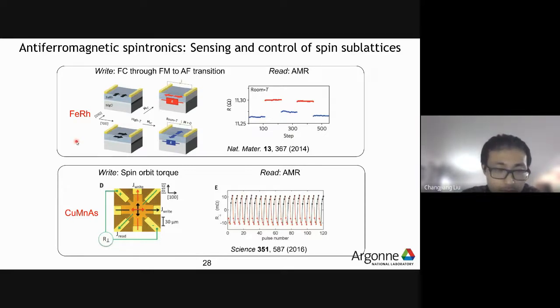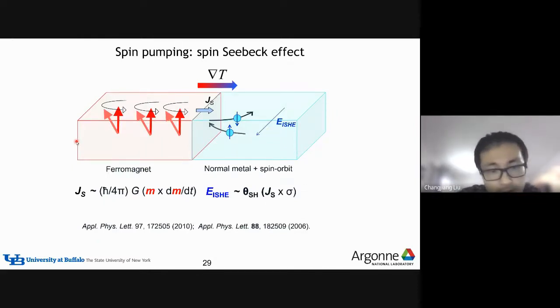So the experiment I will be talking about is based on spin-Seebeck effect, and microscopically, this spin-Seebeck effect is related to spin pumping. So basically, showing in this cartoon, once you have a resonance or the precession of magnetization in a ferromagnet, because of the exchange coupling between the ferromagnet and the conducting electron in adjacent material, this precession of magnetization can inject a spin current into this metallic material.